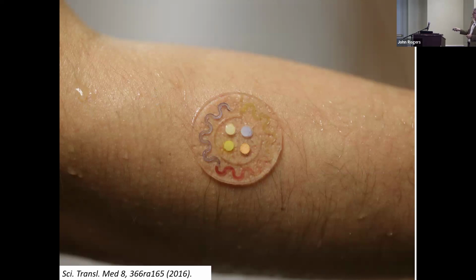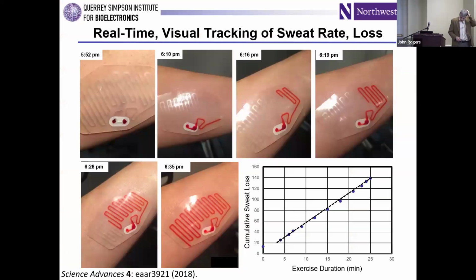This is an example of one of the devices on the outer forearm, compatible even with a little bit of hair. Not a problem. It's a soft material, so it can conform to the topography associated with the hair. And in this case, you can see the sweat is filled up to that 7 o'clock position, and then these reservoirs are filled up. And then what you do is you just take a digital image, and then you do image analysis, color extraction. You get quantitative information out of that. So here's a device on my inner forearm while I'm working out.